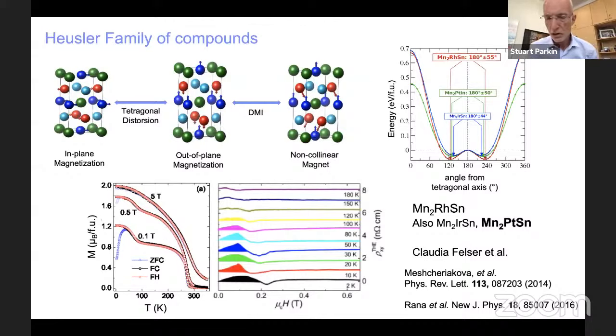Usually they're cubic. The structure is that of 4 interpenetrating FCC lattices, but for those materials which have strong, heavy elements, through spin-orbit coupling the structure can be distorted, tetragonally distorted, and the structure gives rise to a magnetization which is out of plane along this tetragonal axis. So it's a strong interplay between the magnetism and the structure. And at the same time, those same heavy elements, through the same Dzyaloshinskii-Moriya interaction, can give rise to a non-collinear magnetic structure. This work I'm discussing is work we're doing closely with Claudia Felser and her group,